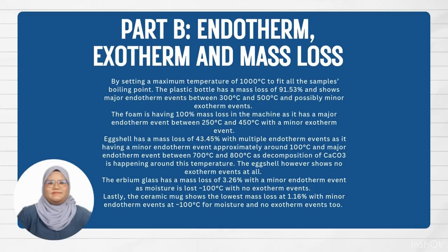Next, part B, endotherm, exotherm, and mass loss, aka the thermal properties for the samples. We are setting a maximum temperature of 1000 degrees Celsius to fit all samples' boiling point. Firstly, we will go through the polymer samples. The plastic bottle has a mass loss of 91.53%, and it shows major endotherm events between 300 degrees Celsius and 500 degrees Celsius, and also possibly minor exotherm events. Next, the foam is having 100% mass loss in the machine as it has a major endotherm event between 250 degrees Celsius and 450 degrees Celsius with a minor exotherm event.